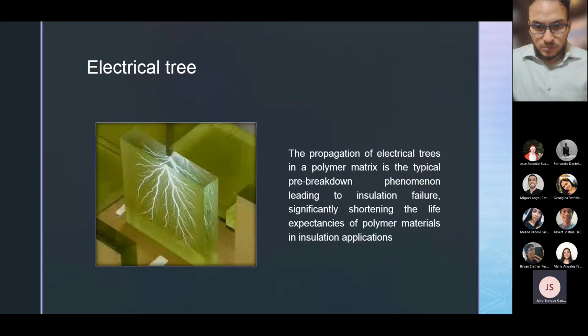Okay, what is the electrical tree? In electrical technology, especially in the high voltage insulation field, polymer materials have been widely applied due to their excellent electrical, thermal, and mechanical properties. There are many kinds of polymer materials, such as polyimide, epoxy resin, polyethylene. The propagation of electrical trees in a polymer matrix is the typical pre-breakdown phenomenon, leading to insulation failure and a significant shortening in the lifespans of polymer materials in insulation applications.